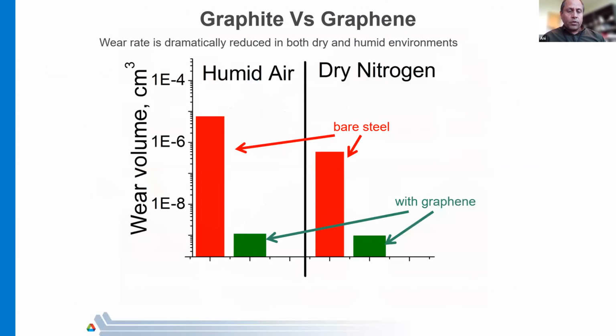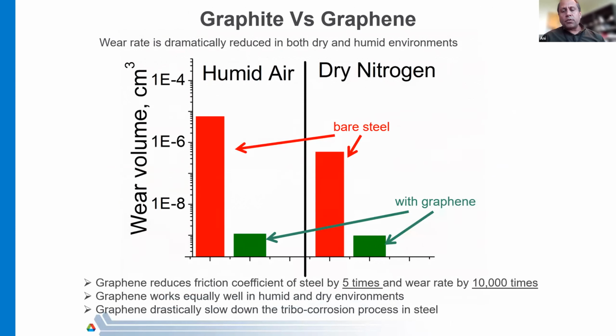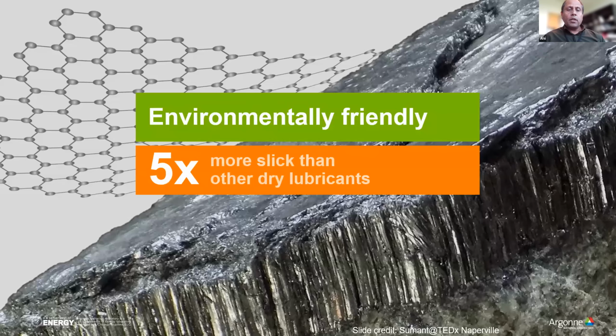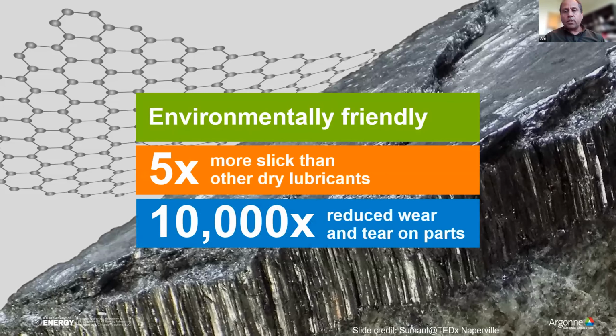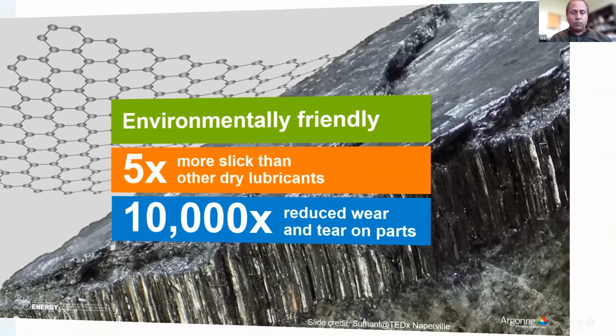So as compared to steel against steel, we see a dramatic reduction in the friction and the wear: as you can see, in humid air, in dry nitrogen, 5 times less than steel, and the wear is reduced by 10,000 times. So definitely, just a few atom-thin layers of this graphene can do this wonder. It was very interesting to see that, and there are no environmental hazards. Basically, when this graphene wears down, it is oxidized graphene oxide on your surface, just like on your barbecue, when you scrape it, what you have left. So this is easily degradable in the environment, but it gives 5 times lower friction and 10,000 times reduction in the wear. So that was very impressive to see.